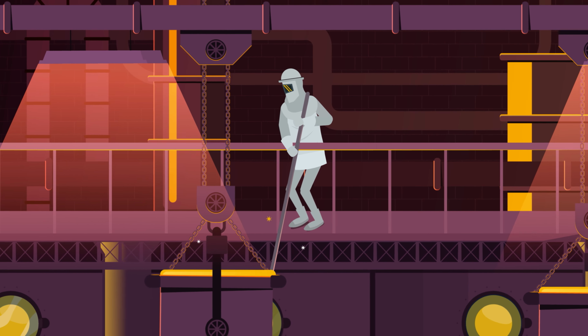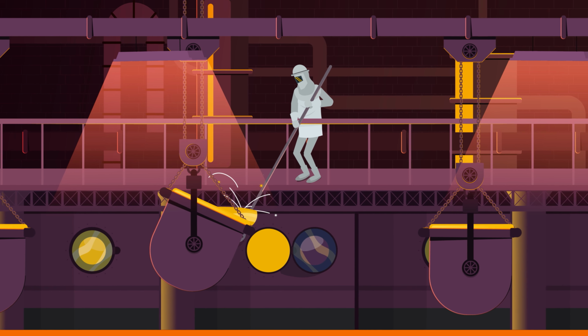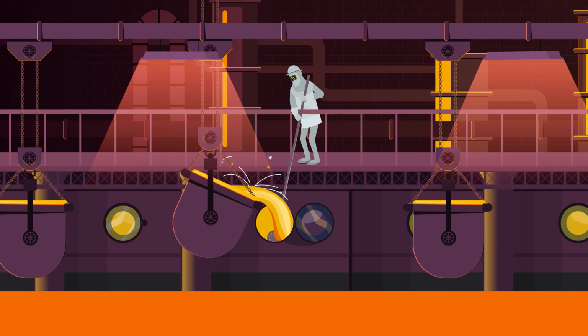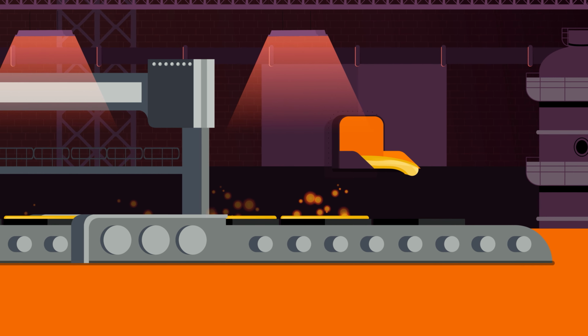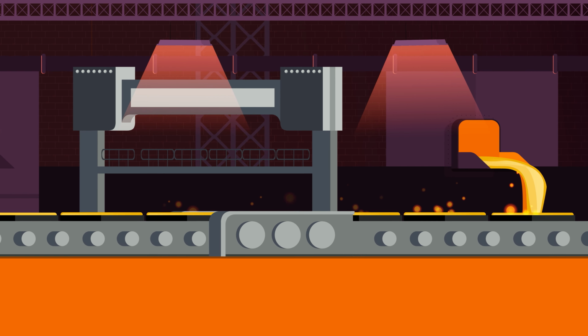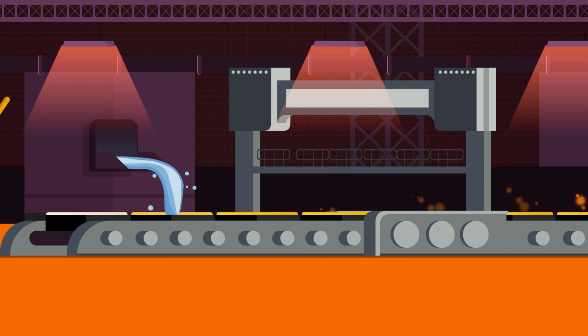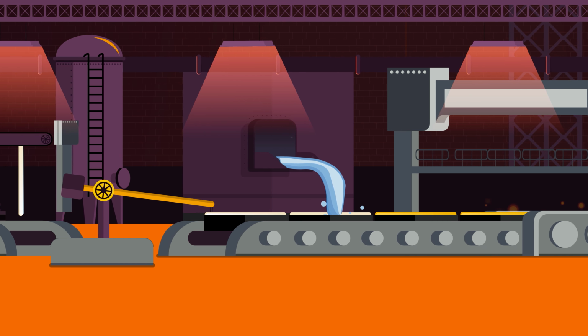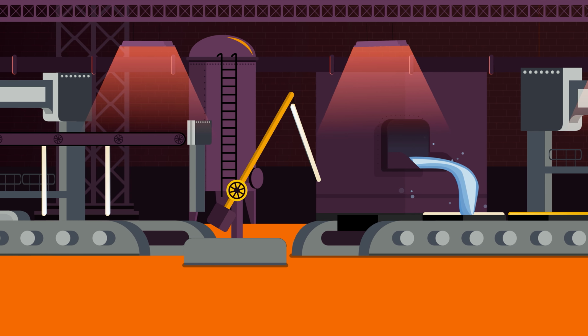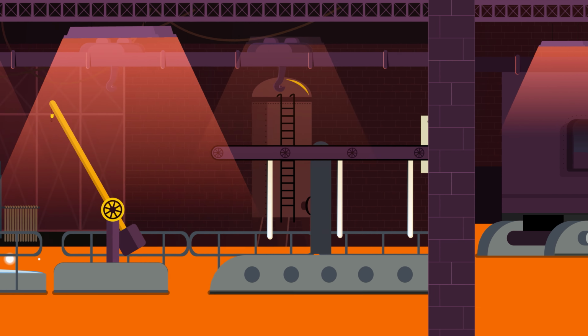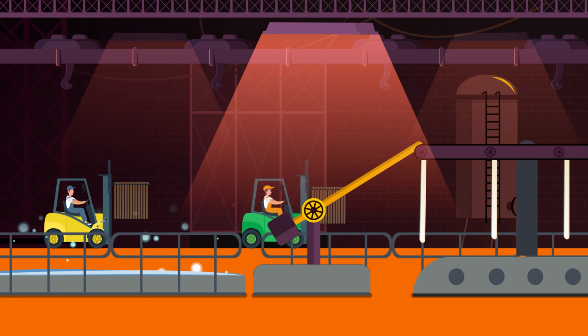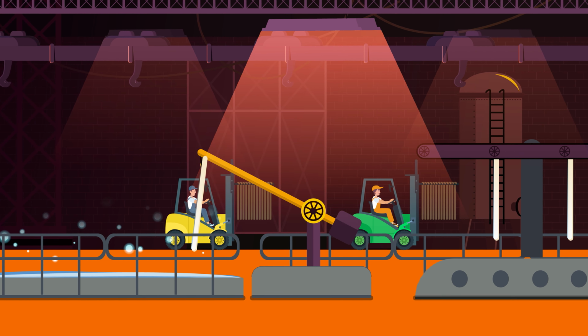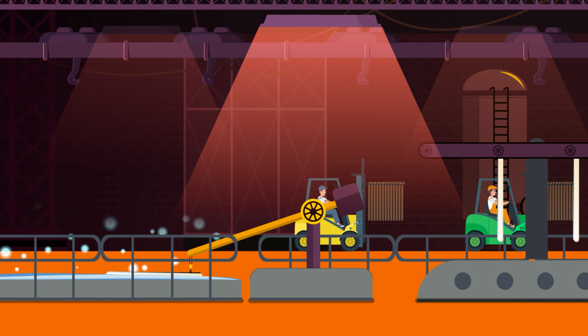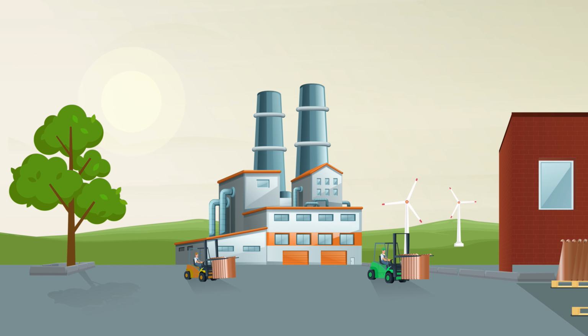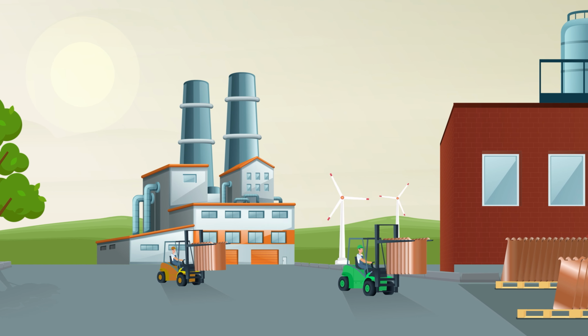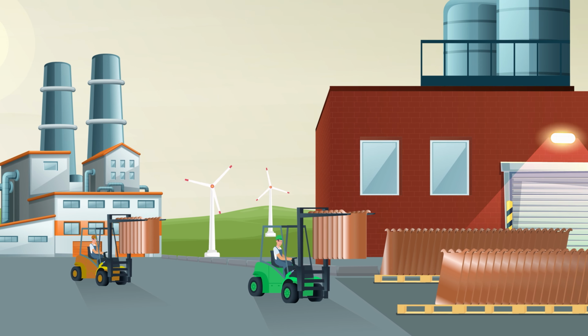Once metal is completely freed from sulfur and iron, the smelters cast large copper plates known as anodes. These 408-kilogram plates are poured into molds, where the surface solidifies as water is sprayed to clean them because the water evaporates instantly. However, the raw copper still contains nearly 1% impurities, requiring further purification. Therefore, the anodes are processed in a massive hall where workers deliver 3,400 anodes daily.